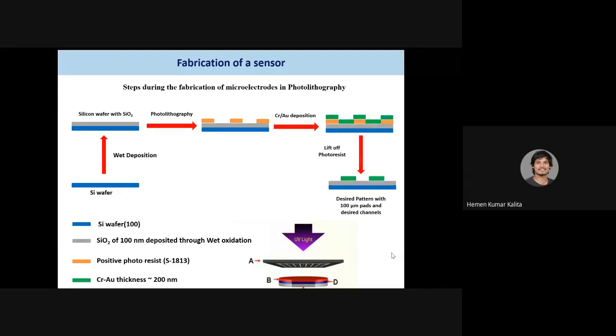Now, depending on this mask, A, the light will partially fall on some region and it will not fall on some region. This A is basically a mask which will allow light to pass on some portions and block it at some portions. If you see the top image, these orange portions are the photoresist which is left after developing. As I already told you, for photoresist, the portion which is exposed to the light is removed by the developer, that is the positive photoresist. So the gap is where the light is exposed and it is removed by the developer. This is the remaining photoresist which is not exposed and it remains on the top of the silicon dioxide. So we get a structure something like this: silicon dioxide and these orange strips.